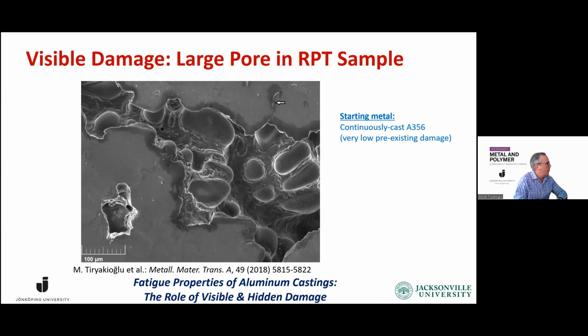Now, you're seeing a pore that was created by entraining some air, by pouring the metal from a height, and it was allowed to solidify in a reduced pressure test. So the pore was quite large. So we were looking at it, although our starting metal was of high quality with very low pre-existing damage.